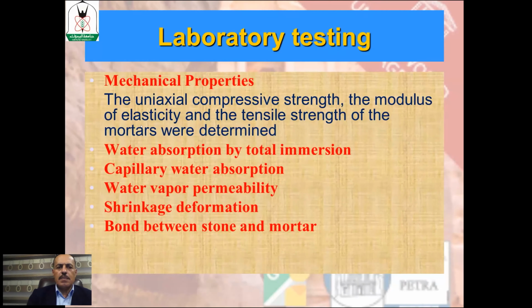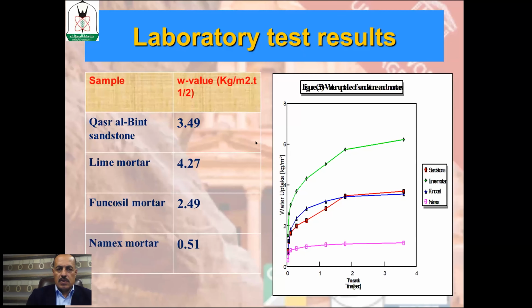The laboratory testing program includes mechanical properties, determining the uniaxial compressive strength, the modulus of elasticity and tensile strength of the mortars, water absorption by total immersion, capillary water absorption, water vapor permeability, shrinkage, deformation, and bond between stone and mortar. So again, I will show you some of the results of the laboratory test program.